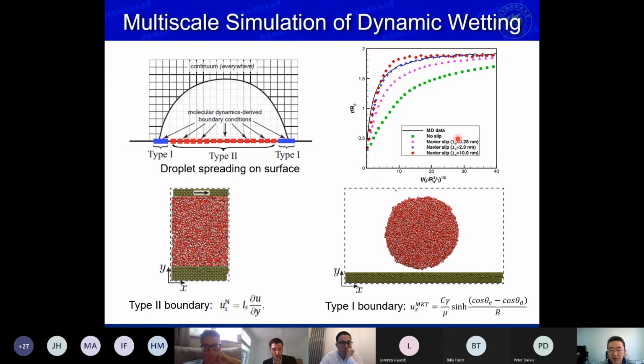But unfortunately, if we use the physical slip length, because for this case we simulate a hydrophilic case, the slip length is very small. It's just 0.28 nanometer. As you can see, the spreading rate is still lower than the NEMD data. To match the NEMD data, we have to use an artificial, very large slip length. Obviously, it's unphysical. The problem is that actually at the contact line region, there is a particular slip behavior. The slip is much larger than that predicted by the Navier slip. And here we use the slip model called the MKT model. I will talk about it afterwards.